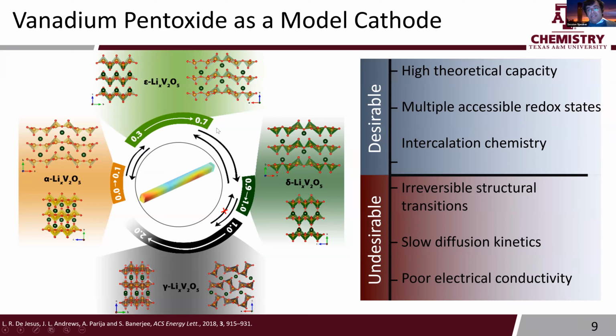So lots of great properties that straight out of the gate we get out of V2O5. It's got a pretty high theoretical capacity of about 440 milliamp hour per gram. You can access multiple redox states, and you can do intercalation chemistry very readily in these galleries between the layers of V2O5. The undesirable issues that people quickly found out,